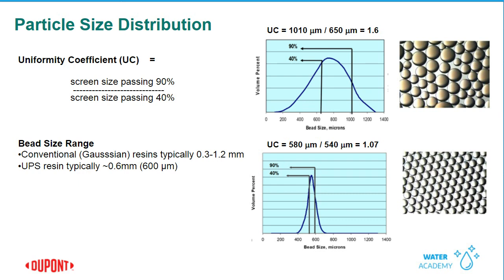Uniform particle size resins generally have a 1.0 to 1.15 uniformity coefficient, whereas Gaussian resins are around 1.6. There are narrow particle size distributed resins, which could be a screened form of Gaussian resins, where large and small particles can be removed, and that will have a uniformity coefficient somewhere in between. And so let's take a look at two examples here. The top is a Gaussian particle size distribution, and the bottom is a uniform particle size distribution.